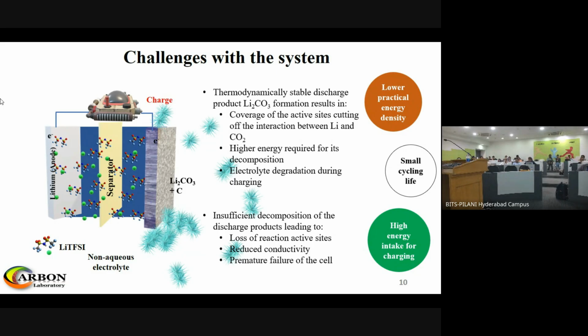With these challenges, the practical issue we face is lower practical energy density. Of course, the theoretical energy density might be very high compared to lithium ion, but when we go for the practical cell, because of these reasons, the actual energy density is very low. There is also a short cycling life; in fact, only a few cycles were demonstrated in the beginning. And there is high energy intake for charging. So it is not an energy efficient process, because the charge voltage is higher than the discharge voltage which is generated.